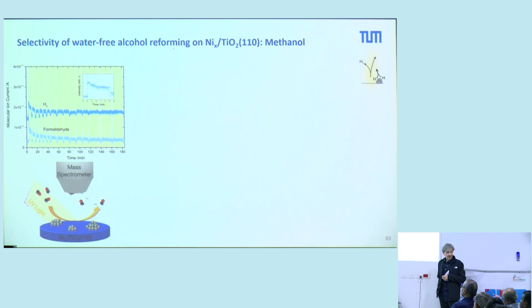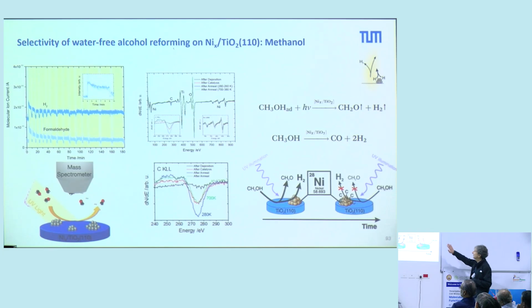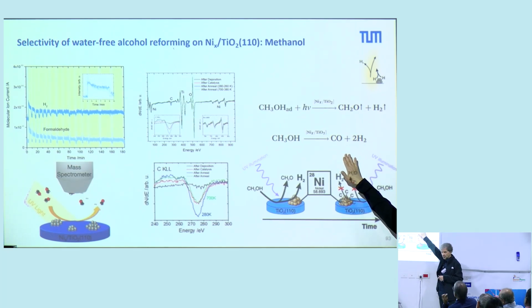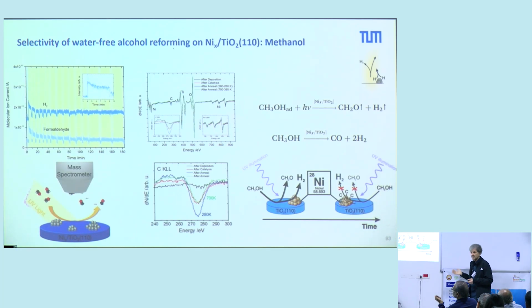Platinum, we would like to replace by nickel. Nickel is known as a very good hydrogenation catalyst, but we see that it is poisoning. That means if you do the reaction, the reactivity is decreasing as a function of time. In this case, we have another reaction taking place on the nickel. The nickel adsorbs methanol, and then it is known that it produces CO and H2. We also showed in our very first experiment on size-selected clusters that small nickel clusters can dissociate CO. That means you produce a carbon layer on the nickel and you are poisoning your recombination catalyst. Therefore, it is cheap, but it's not working.